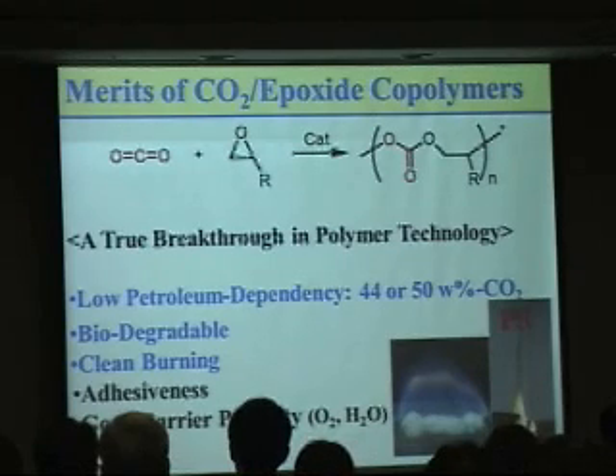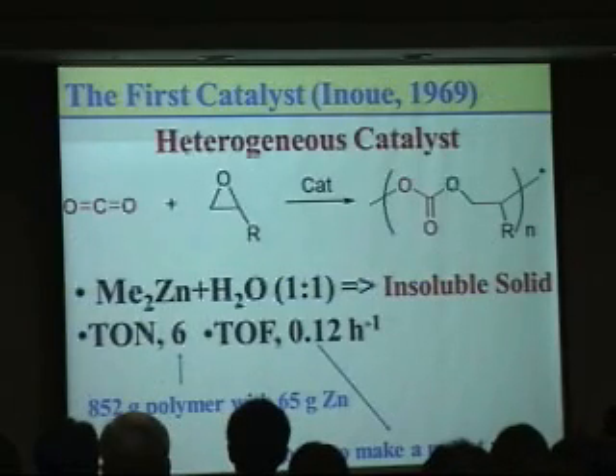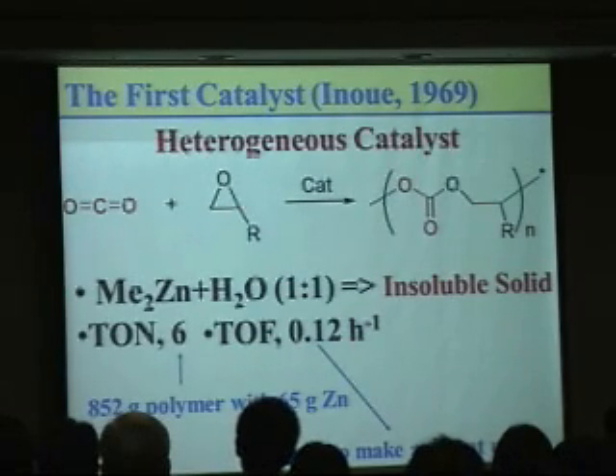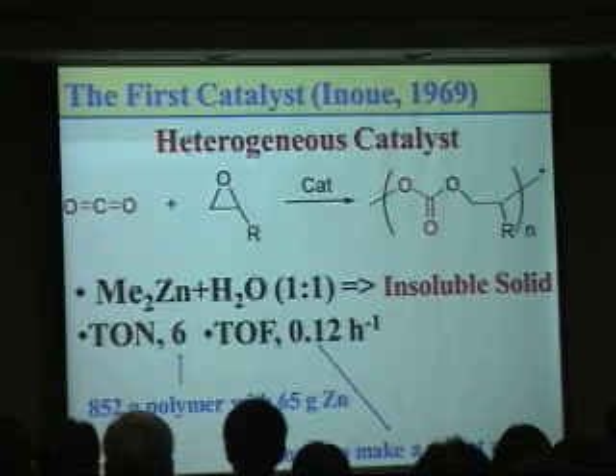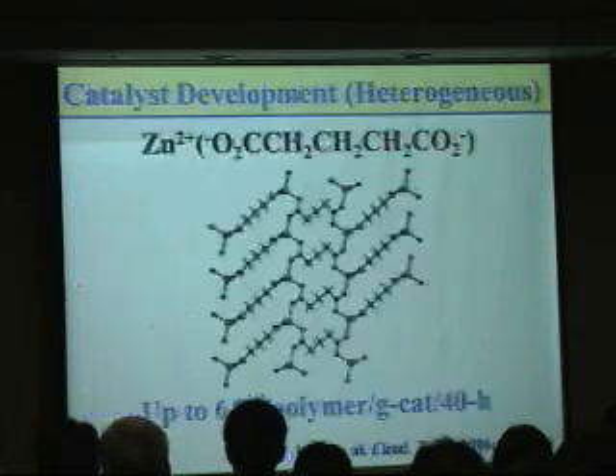Because it contains polar groups, it shows good adhesiveness and it displays very good barrier property for both oxygen and water. The first catalyst was introduced 40 years ago, a long time ago. It was a heterogeneous catalyst prepared by mixing dimethyl zinc and water in a 1-to-1 ratio. It is not soluble, so it is a heterogeneous catalyst. The first catalyst shows very low catalytic activity.